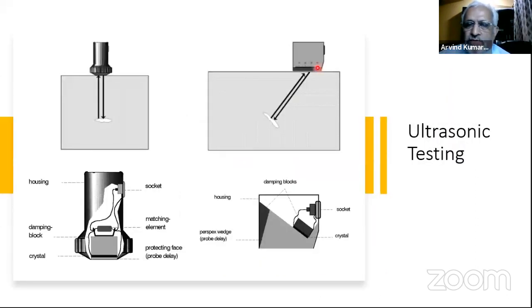Angle probes, this is how, if it is 45 degrees, the ray will come out at 45 degrees, 60 degrees will come at 60 degrees, and like that. Straight beam goes straight at 0 degrees, hits the indication, and comes back. Here, if the defect is large, the entire